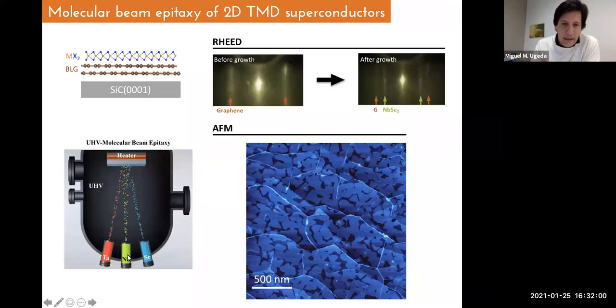For example, let's say niobium diselenide, we start from the pure elements and we evaporate it against a heated surface, for example, graphene, in order to grow one monolayer, two monolayers, whatever you want. We previously grow or clean our substrates with a heater facility that we have here. So everything grows in ultra high vacuum environments.